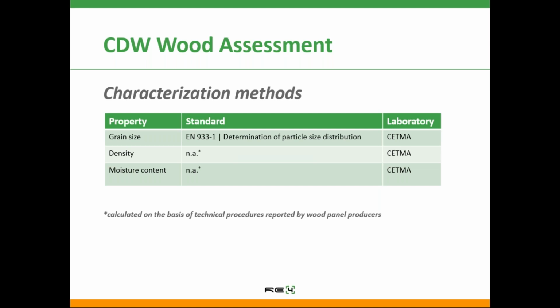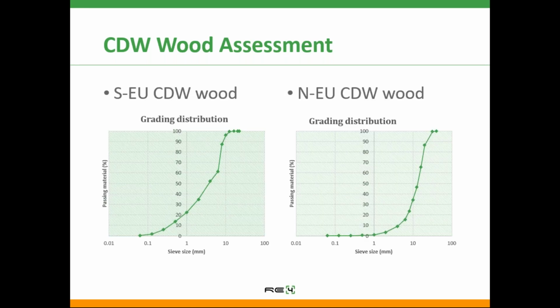In this table, the methods used for the geometrical and physical characterization of the construction and demolition waste lightweight fraction are summarized. When no standards were available, technical procedures reported by wood panel producers were used. The wood fraction has been characterized to define particle sizes. Two different characterizations have been carried out. The first one, according to the methodology described in European Standard 933 Part 1, has been a one-dimensional sorting in order to determine the ratio of powder or near-powder size particles on the total amount of material. Moreover, first data on size distribution have been acquired. For each batch of wood fraction, 8-liter volumes have been tested with this method.